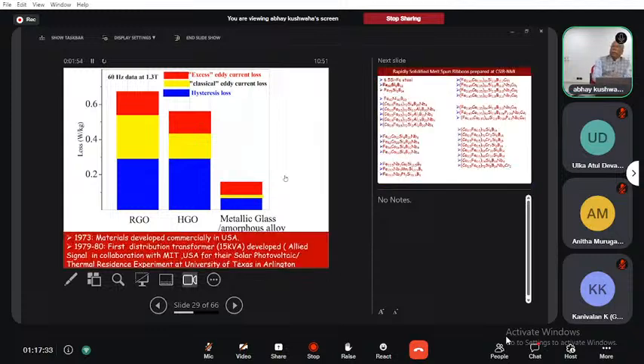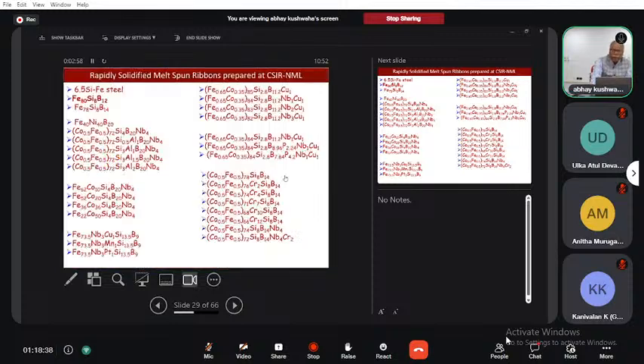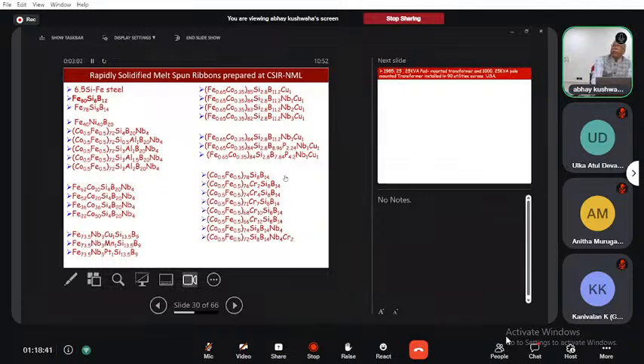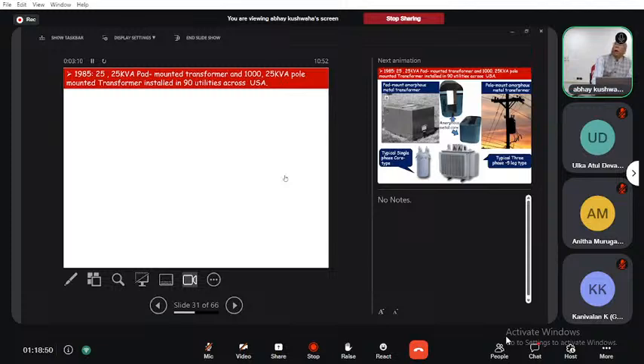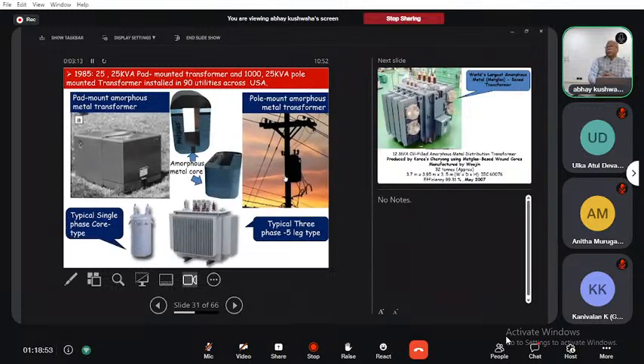And this material was first developed in 1973, and after that, in the USA, the temperature rise came down to almost 34, 35 degrees Celsius. So there is a lot of advantage of using these materials. And there is a large number of alloys which were developed at the National Metallurgical Laboratory. And you see, these are the various transformers. And basically, there are industries already developed in India who are producing this material commercially.